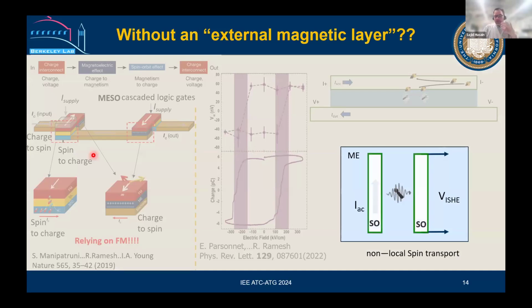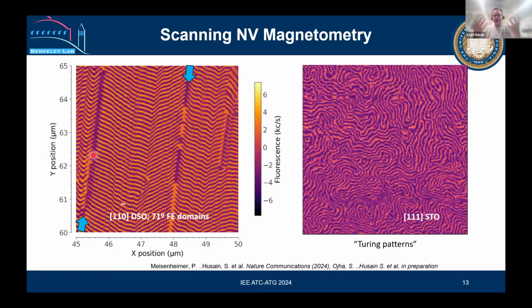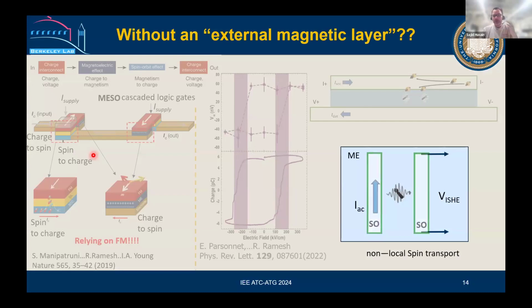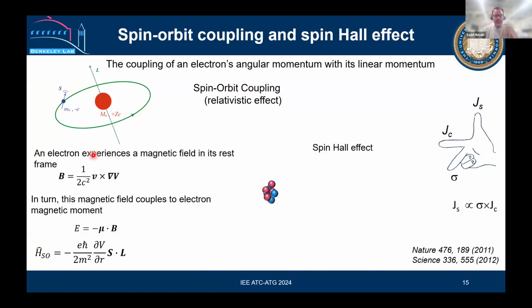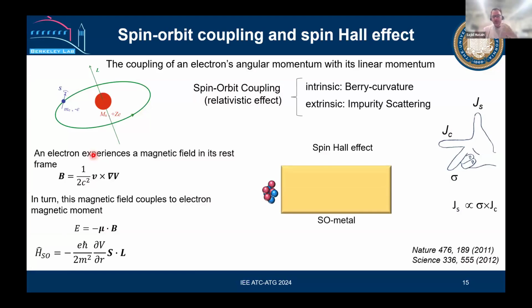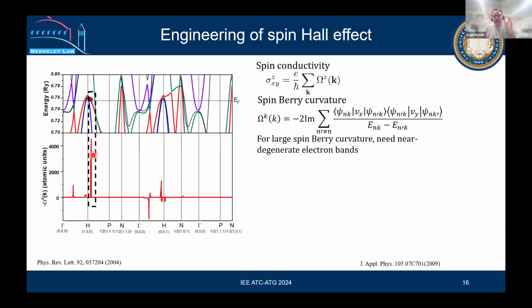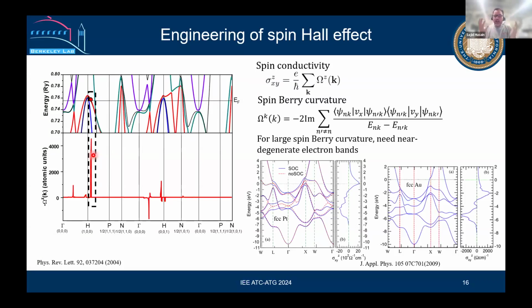Okay, now some spin orbit coupling, because, as I said, we need to enhance our output. So we are doing a lot of other external engineering to improve the system to make it work as we propose, to get 100 millivolt output. And spin orbit coupling is again an important part to understand. I don't want to go into the detail, but with a simple spin orbit coupling material you can polarize your current, and intrinsically the Berry curvature is very important to play with. And if you clean up your material in a good way, you can enhance this effect a lot.